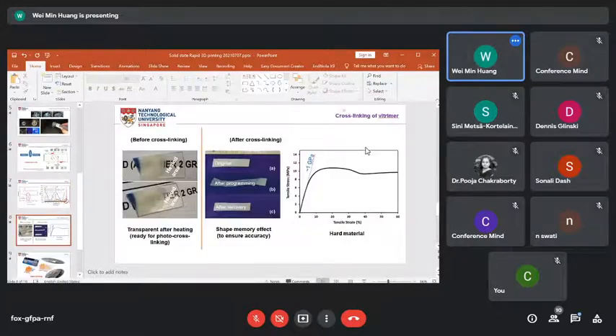Now, to enable vitrimer to be 3D printed using UV, we need additional requirements. The first is transparency. Over here, it shows that the material is transparent, but only if you heat it up. This part has been heated up to above its melting temperature, but this part is without heating to its melting temperature, so the material is still opaque. But this part, if you heat up to above its melting temperature, the material is transparent, so that the laser beam can pass through it. Okay, this is very good for cross-linking using UV.